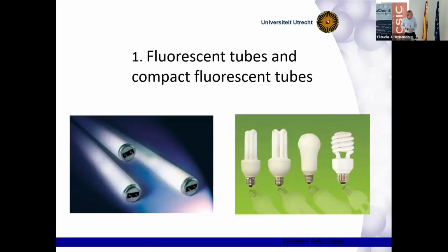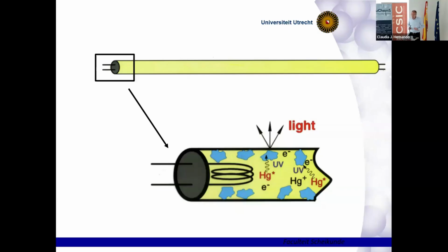So first, fluorescent tubes and compact fluorescent tubes. It works as follows. You have a glass tube. In the glass tube there's a little bit of mercury. You turn on the fluorescent tube, the mercury evaporates, and then current passes through the mercury vapor. The electrons are accelerated from the negative to the positive electrode, collide with the mercury atoms, get to an excited state, and return to the ground state by emitting light, but UV radiation, mostly around 254 nanometers. The process is very efficient, about 70% energy efficiency. So if you put in 10 watts of electrical energy, you get 7 watts of UV radiation out. The problem is you cannot see it.